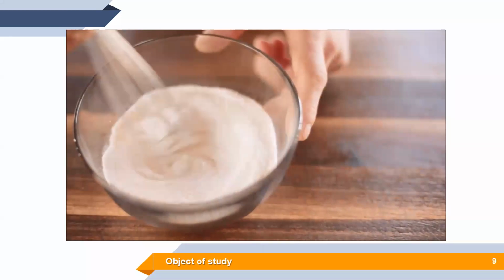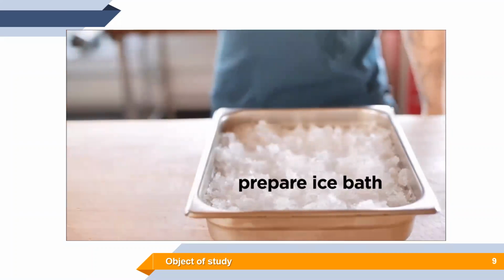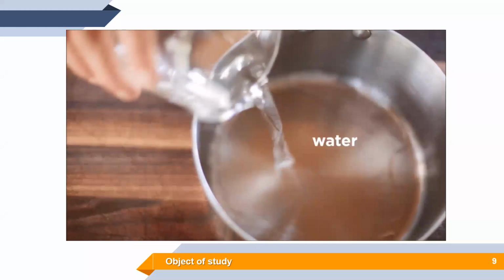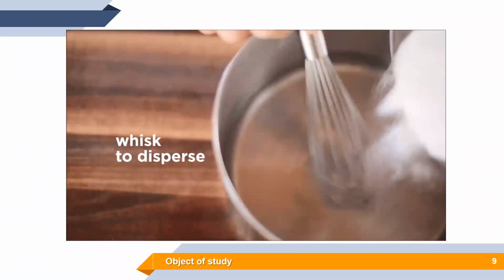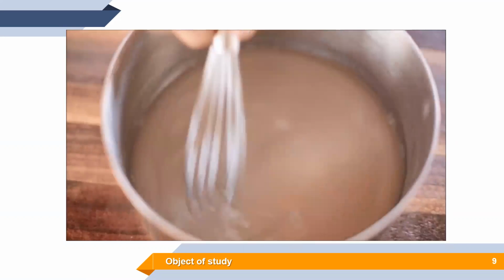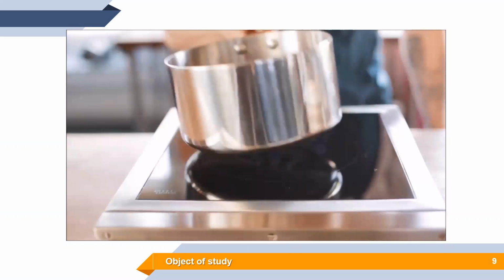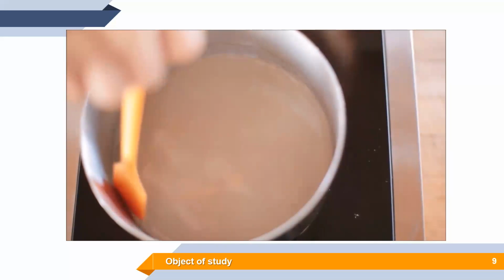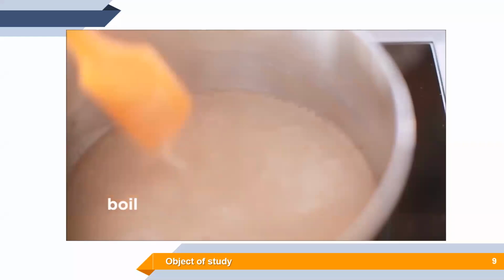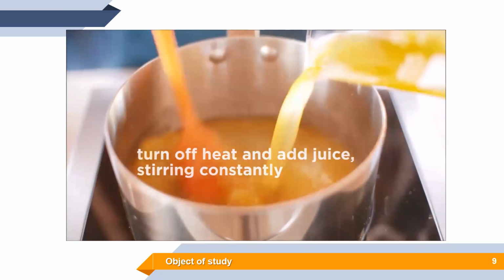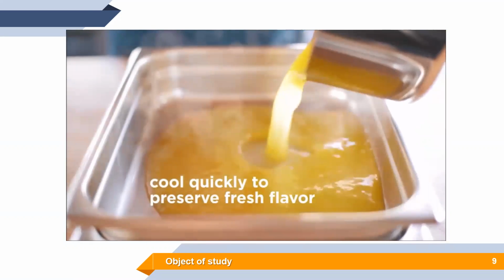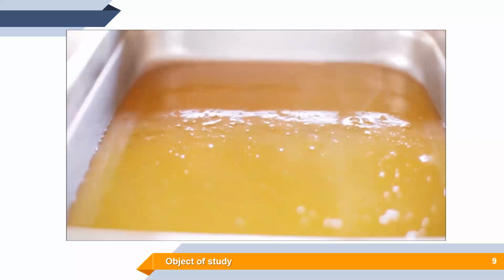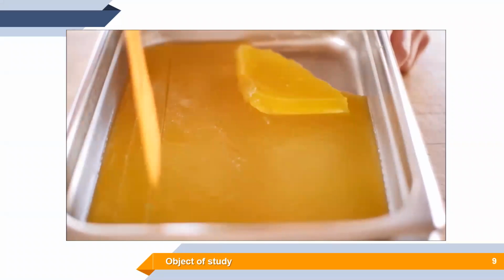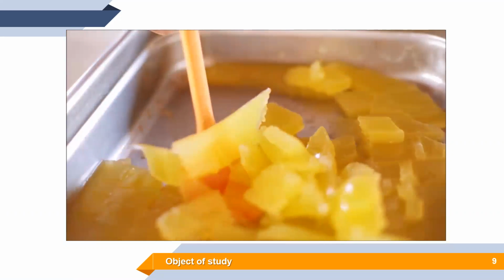And what we do actually is dissolve this gelator in the liquid electrolyte solution. This phase of the process usually involves high temperatures around the boiling point of the solvent, just to dissolve and melt all the molecules of the gelator. But when everything is dissolved, then it is enough to cool down this mixture containing gelator and the ions to transform the liquid sol phase into gel phase, what you can observe here. At the end, we result with a material which is very similar to what we observe on this picture.